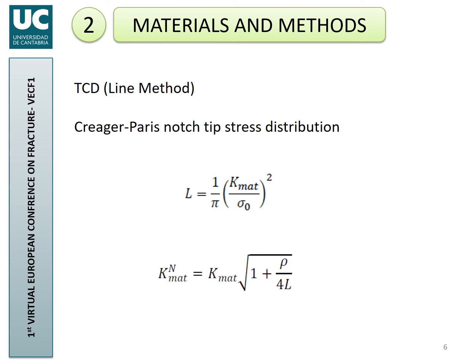And because we are dealing with notches, we are also going to use the theory of critical distances, and particularly the line method, which combined with the Creager-Paris notch stress distribution provides us the expression for the apparent fracture toughness shown below, where the apparent fracture toughness is equal to the fracture toughness multiplying the square root of this factor shown in the slide.